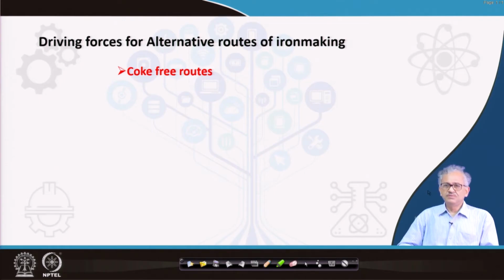We have very limited coking coal reserves, and that too the coking coal has another problem of high ash content. So, we are dependent on importing coking coal, and then we do the coking process in India. We mostly depend on import of coking coal from Australia, and of course we blend it with non-coking coal or other medium coking coal, and then we charge it into the coke oven, sometimes in the form of stamp charging, as we have discussed already. But still, the coke becomes very costly, and as I said, it constitutes around 50% of the total cost of hot metal production.